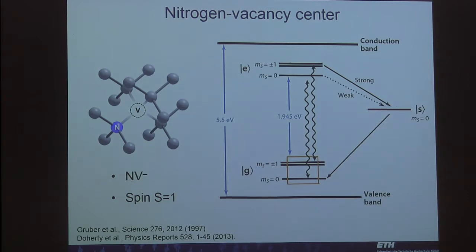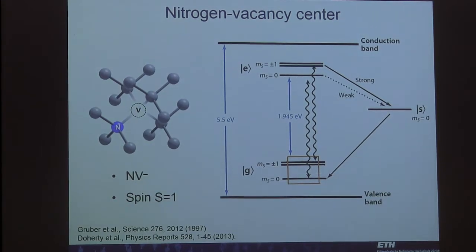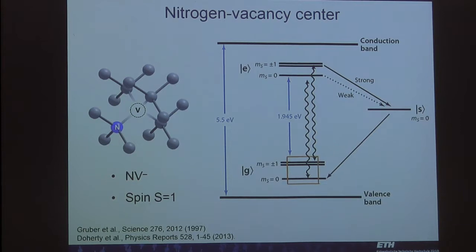In most cases, if your laser energy is higher, so wavelength is lower, you can still excite the system. But now the energy is higher, so your electron is technically in a higher energy level, and it has to give away the excess energy to phonons. So in this case, phonons are created. The zero phonon line means that if you excite the electron, no phonons are created. All the photon energy put in goes 100% into the electronic excitation. This is why the emission spectrum is really broadband, because it spans several nanometers.